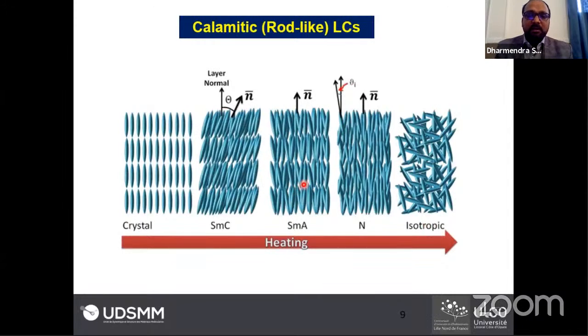Okay, so basically in calamitic rod-like liquid crystals, when you heat a liquid crystalline compound from crystalline to isotropic liquid, you can obtain different liquid crystalline phases in between. Most common phases are nematics and smectics, such as smectic A and smectic C. In the nematic liquid crystal, the molecules obtain an average molecular direction that we call the director. So the director is the average orientation of the molecules.